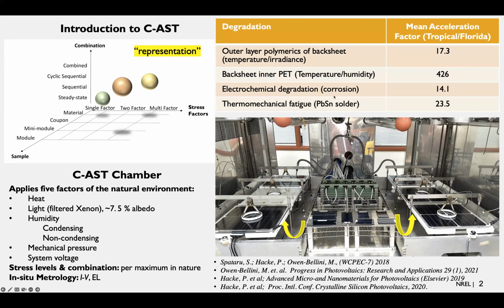In other work, we've examined the acceleration factors of some particular degradation modes and mechanisms. For items such as the outer layer polymeric and the inner layer PET, electrochemical degradation and thermomechanical fatigue, the acceleration factors are in this range here. Some things to point out is like PET, the acceleration factors about in the 400 range, but that's associated with the high activation energy of the degradation of PET in temperature and humidity, leading to a great deal of acceleration.